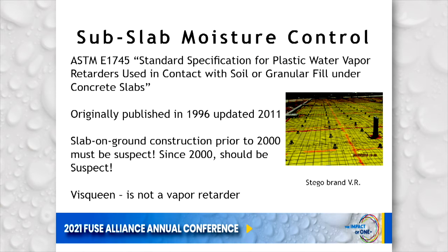When we talk then about subslab moisture control, there are times when you could be held responsible for knowing this information. ASTM E1745, which is the standard specification for plastic water vapor retarders used in contact with soil or granular fill under concrete slabs, was originally published in 1996 and updated in 2011. Arguably, that's not that long ago.